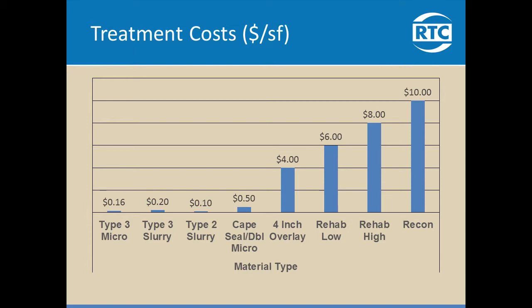We had one section of South Virginia Avenue, which was about 3 miles long, a major roadway. It was an NDOT road that was turned over to our city, and it had an open graded surface course that was raveling off, and so it was incredibly rough. It had about an inch of profile that needed to be fixed, and we fixed it with a double microsurfacing that was done at night over a week on this high trafficked area,